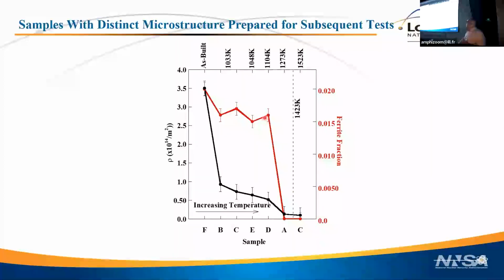The ferrite is more persistent. So the red is plotting the ferrite fraction. It persists pretty unchanged up to about 1,000 Kelvin, or what is that, 800 or 700 and something C. Sorry, I can't do that math on the fly. But you see what this gives you. This gives you a recipe if you want to pull out one part of the microstructure but leave another one. This gives you the recipe to do that, which is really what we're all about. How do we do informed heat treatments?